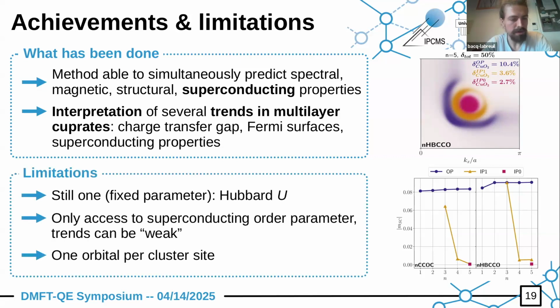About the limitations, I think that it's important to state them now. For now, we still have one fixed parameter in this study, which is this Hubbard-U interaction, which is usually the problem with our type of approaches. But this is still something that we have to set by hand. At present, we only have access to the superconducting order parameter to describe superconductivity, so we cannot make claims about critical temperature directly. And the trends that we obtain can be seen as, in some sense, weak, unless for the inner planes where it's really clear. We can also only account for one orbital per cluster site. At present, this is a limit of the impurity solver. But it seems that even in this limited framework, we can understand quite a lot about these systems.